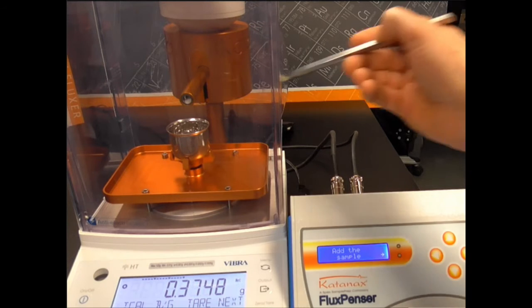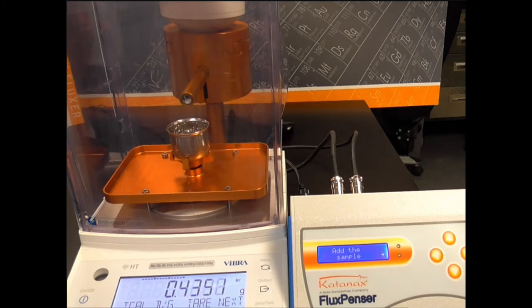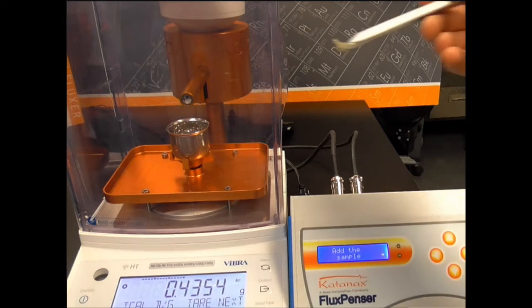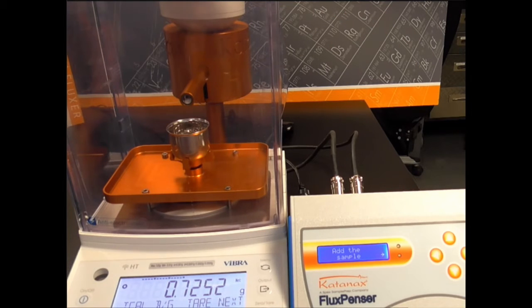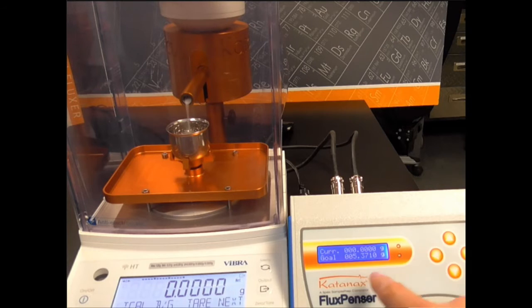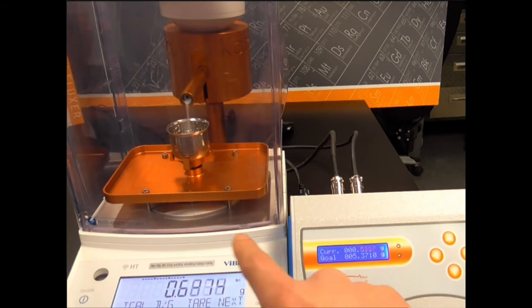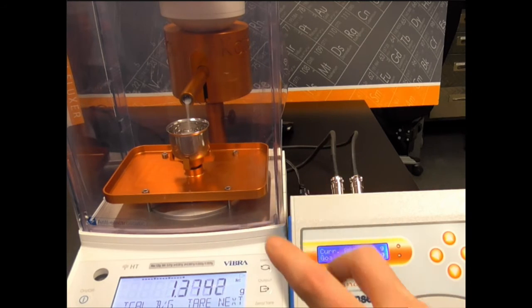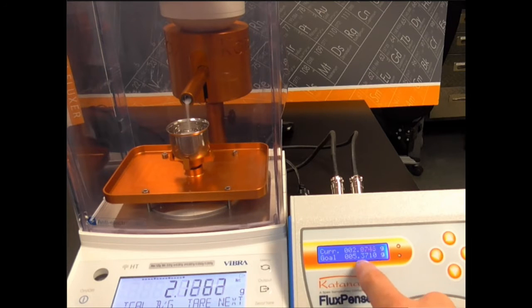It's only because it's related to the size of mold I will use during the fusion. So 0.7 grams of sample will give me approximately 7 grams of flux. That will be good to complete my 32 millimeters mold. So my sample is weighed. You can see I'm not exact, but if I continue here, it will compensate for this non-precise sample weight and will adjust the remaining amount of flux to reach my 1:10 ratio.